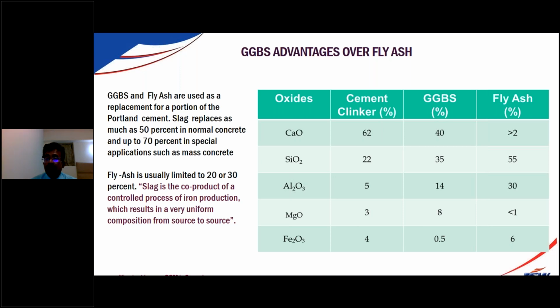But since GGBS has 40% calcium oxide, after 10 hours, when the concrete is set and we walk on the concrete, it should not make any impression. Maybe 10 or 12 hours, the GGBS will immediately start reacting so that there is no tremendous drop of strength in the concrete. Those people who have the mindset that if I use GGBS, strength will be reduced, you have to remove that from your mindset because this has calcium oxide. That is the beauty of the product.